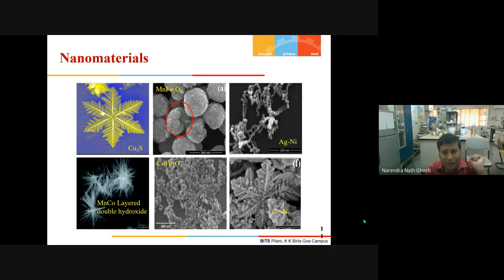And the beauty of these is that when we are talking about compositions of more than one element, like cobalt nickel, silver nickel, manganese cobalt, with our technique we can manipulate the compositions. Manganese ferrite and cobalt ferrite are magnetic in nature, and cobalt nickel is also magnetic. Why are we interested in magnetic nanoparticles?